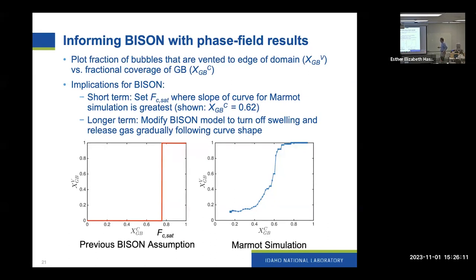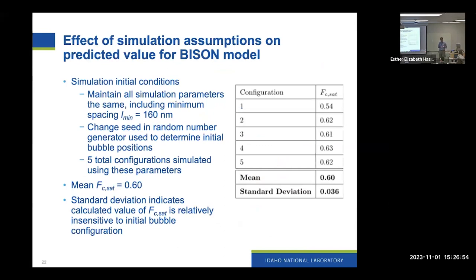So what we did was plot the vented fraction versus the fractional coverage, and you see that it's not a sharp spike like that, but it does increase rather rapidly at some point. So in the short term, what we've done basically is figure out where the slope of this curve is greatest, and said, okay, let's use that for our fractional coverage at saturation. In this case, it was 0.62, which is quite a bit less than that 0.78 value they were using. Longer term, what we'd like to do is account for this more gradual release within Bison, following this curve shape that we've determined from our phase field simulations. But for the time being, there's still a lot we can do that's useful with this single value.